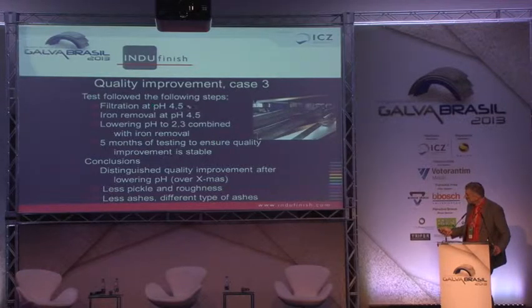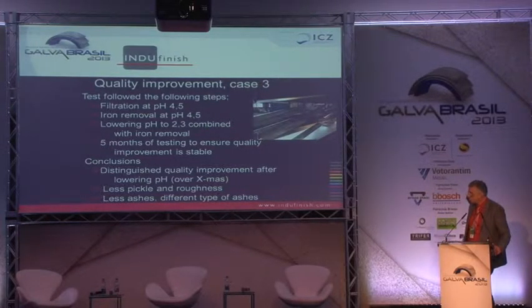This test started with just filtration at 4.5. That gave a little bit of sludge in the filter press. The next step was iron removal at 4.5. Went all right, but not a very dry filter cake. And after that, we started lowering the pH to 2.3. And that's where it all changed.